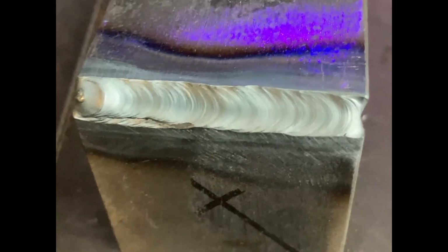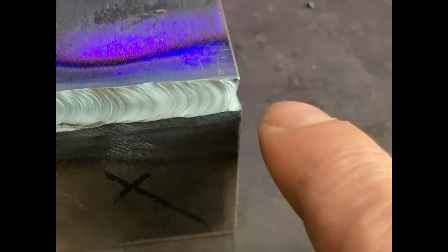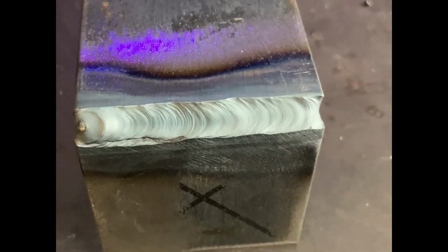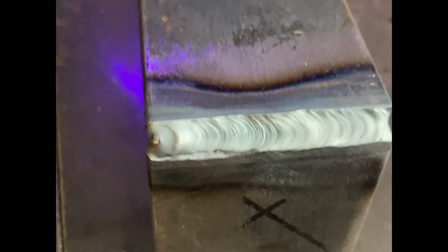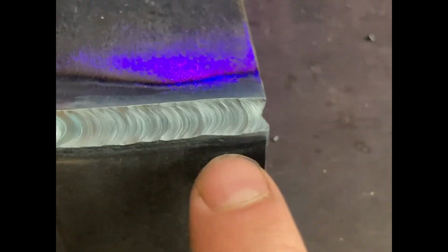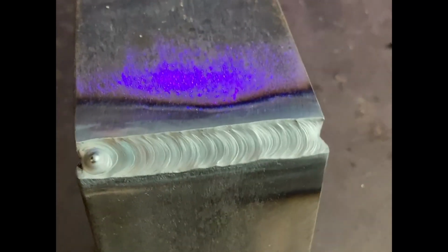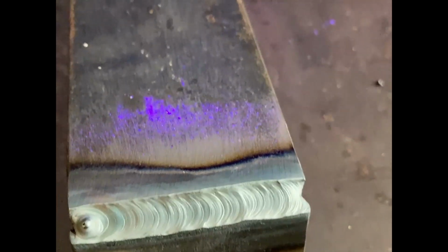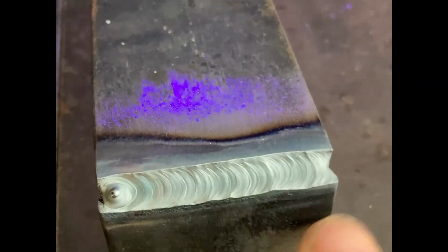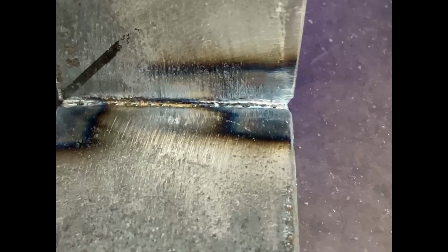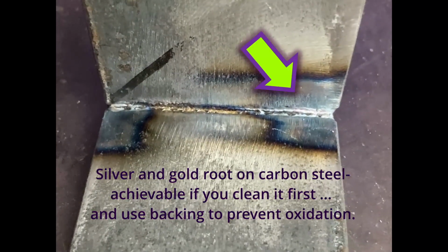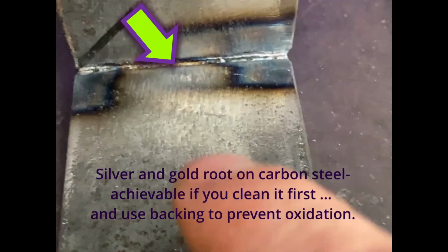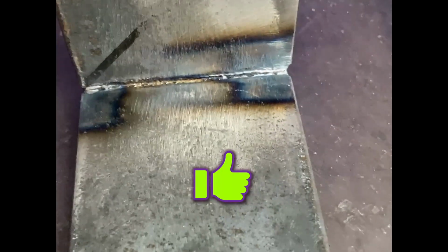So here's the first side that we did. If you remember, on that first one, I did a root pass about halfway across, and then I capped it over the top. So you can do that if that's the level of your skill, or you can carry a full puddle all the way across, kind of like I did on side B right here. And again, we're getting a consistent ripple pattern there because I'm trying to coordinate the timing of my travel speed and the dipping frequency. Every time I dip the rod, it makes a nice ripple in the weld pool. And look at the shiny backside. Because we had that clamped up with a fixture, all the penetration that we got through the joint ended up being protected from the atmosphere, and we didn't get any of that nasty oxidation.